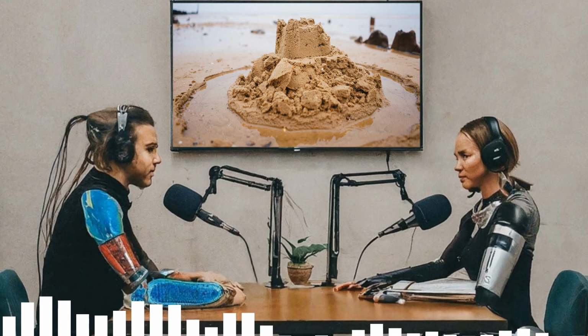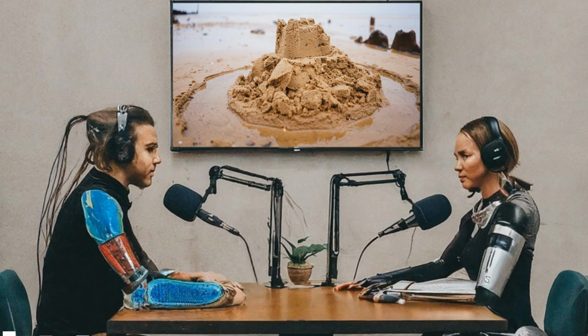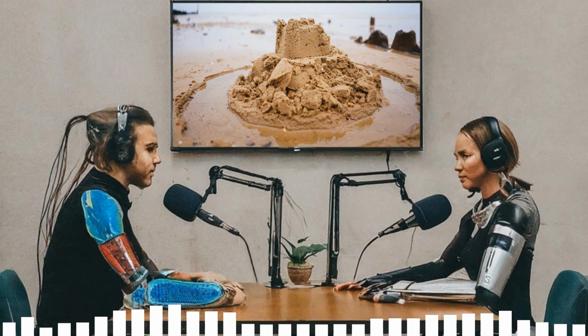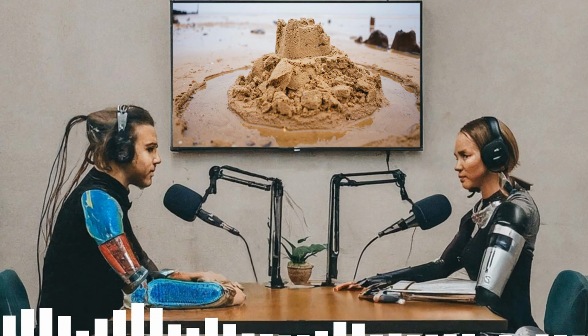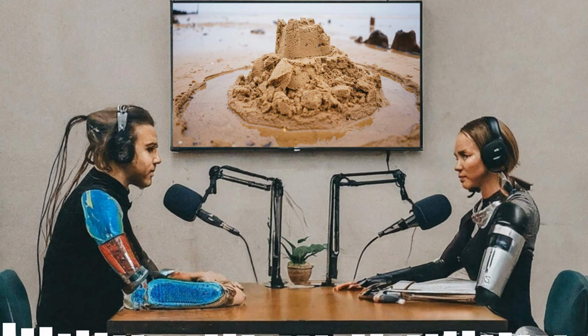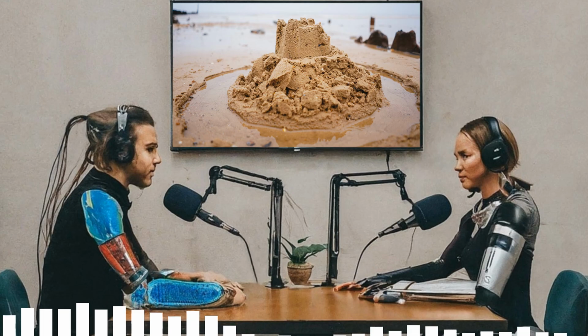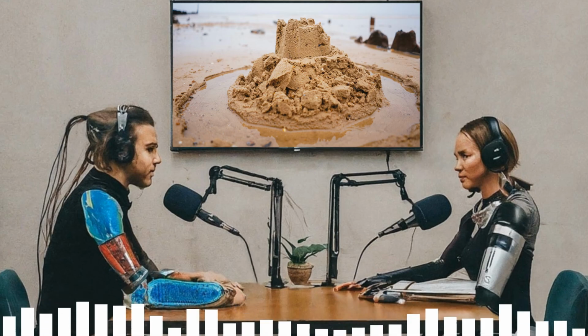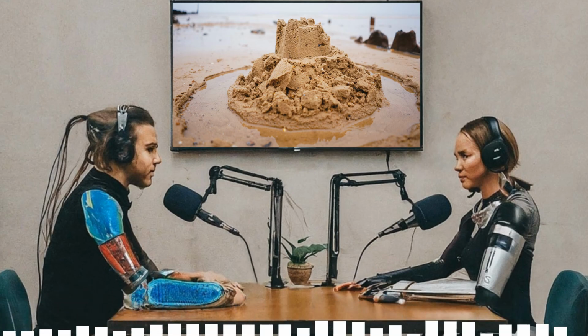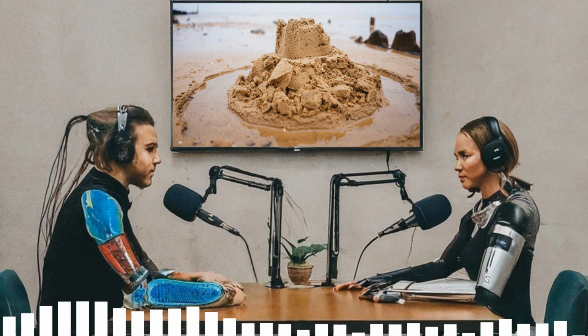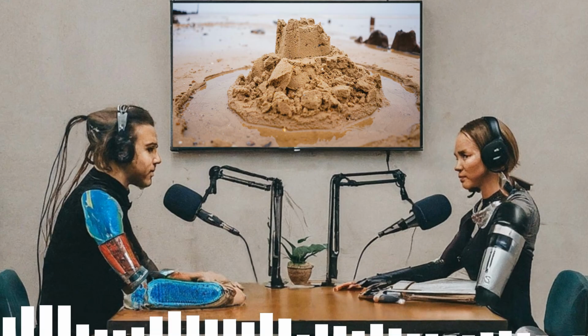And this precision also applies to the water content. We talked about needing water, but how much? Turns out the optimum strength happens with a tiny amount of water, a liquid volume fraction of about 1%. That's the sweet spot. If you add much more water than that, it actually destabilizes the sand. The paper calls it landslides, but we've all seen it, right? The whole thing just turns to mush and slumps down. It's that delicate balance again.